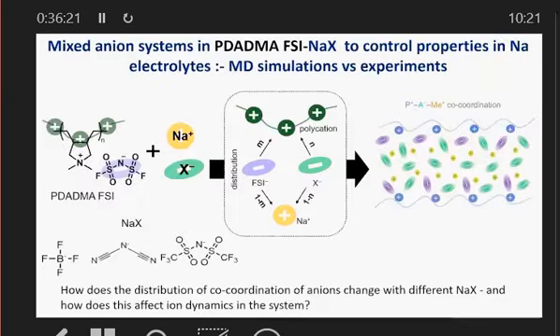Okay, so now I'm going back into the simulation box, and I'm going to look at what happens if we start to try and dissolve different sodium salts, because sodium has been a bit of a problem for us. Some of the FSI works well, but the other ions we have found really hard to dissolve. I'm not quite sure why at this point. So we thought maybe mixing salts will help us get a better behavior. The idea again is to use a polycation to modulate the behavior of the sodium ion by having 2 different, or multiple, coordination environments possible here. And we've looked at the BF4, the DCA, the TFSI system, PF6, and other systems as well.